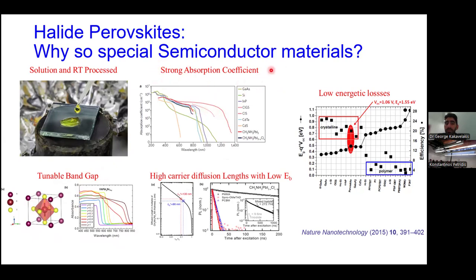What does it mean? With a specific thickness, we can absorb very high. For example, with silicon, we need 100 micrometers or more, close to 300 micrometers thick slab in order to absorb 100% of the incident light. But because of this 1 to 2 orders of magnitude improved absorption coefficient for these materials, they can absorb the same amount of light, close to 100%, even with less than 1 micron. So we have a 300 to 500 times thinner material and device. And this translates to significantly lighter devices and flexible devices. I will discuss this later on.